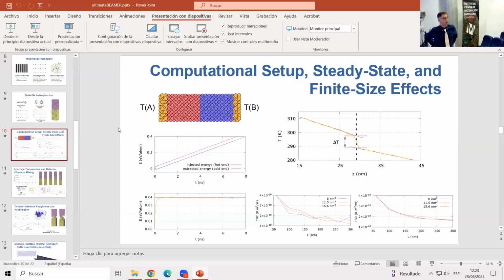Yeah, they cannot pass. Actually, one thing I was thinking when you were showing this is that the scales where you see an increase in the thermal boundary resistance are typically well below 100 nanometers or something like this. And this is exactly the regime where in both materials, germanium and gallium arsenide, you expect to have non-Fourier heat transport. Meaning, in other words, that you are well within the quasi-ballistic transport regime, which in other words is out of equilibrium, right? So my question is, do you think that this could be the explanation for the increase that you see?